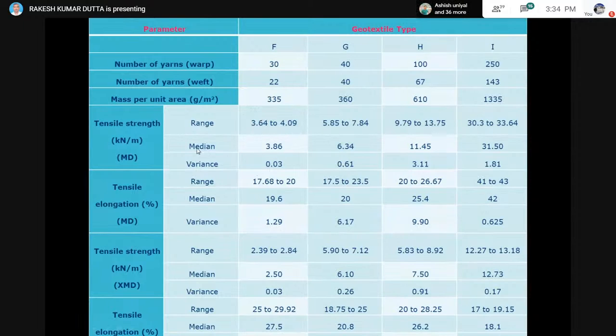Then we took the median of all the 5 samples which we tested in the machine direction as well as in the cross machine direction. Simultaneously, we have determined the variance. So you see, the variance is within the limit. Only 2 to 3% variation is there, but the median values are considered as the tensile strength of these products, with a variance of 0.03 in the first case, 0.61 in the second case, 3.11 in the third case, and 1.81 in the fourth case.